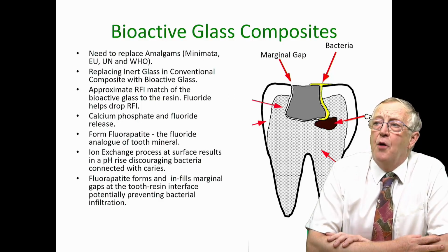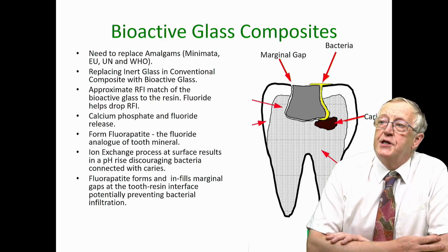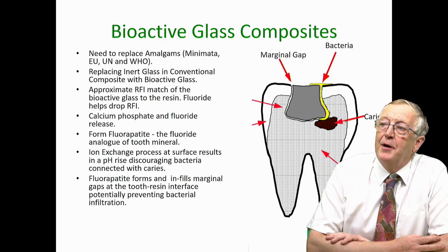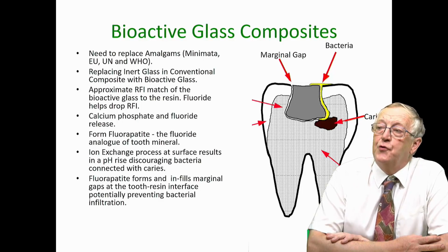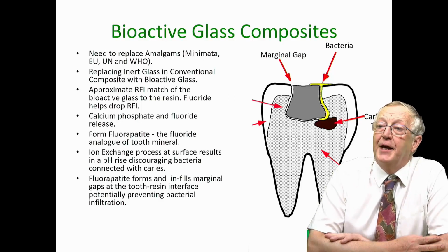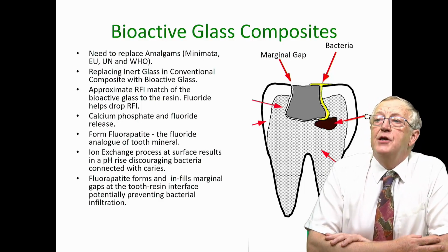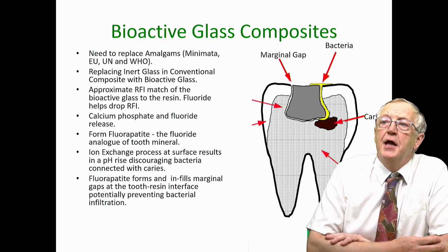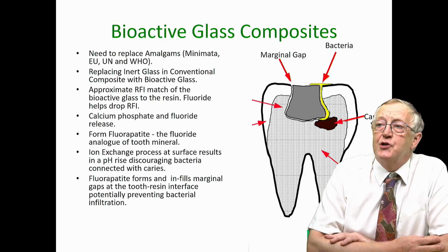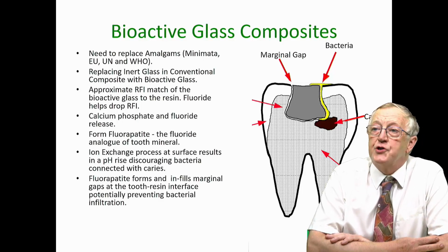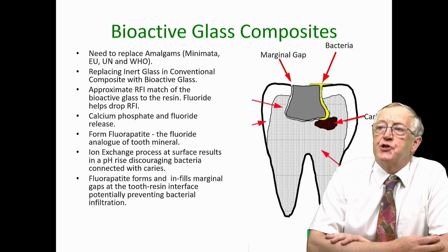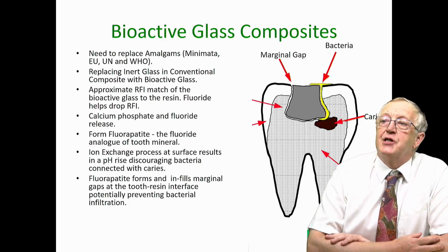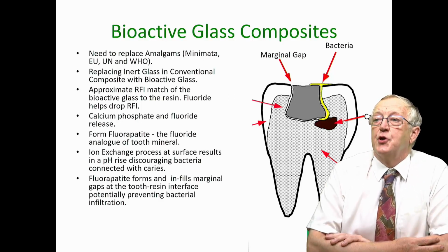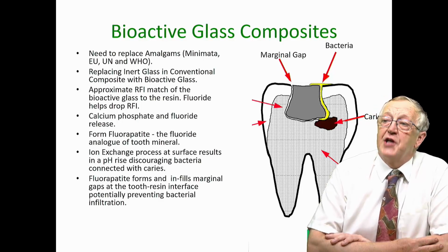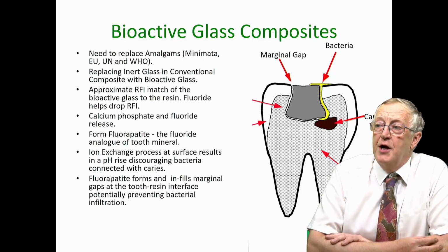The big problem with composites, as we already alluded to, which is shown on the right here, is you always end up with a gap, and bacteria permeate down that gap and they cause secondary caries, or tooth decay beneath the restoration or filling. What we've been doing is replacing the inert glasses used in conventional composites with bioactive glass, and we've been adjusting the refractive index of the glass to match that of the resin so that we get some translucency in the material, which gives better aesthetics but also enables us to cure at greater depth.